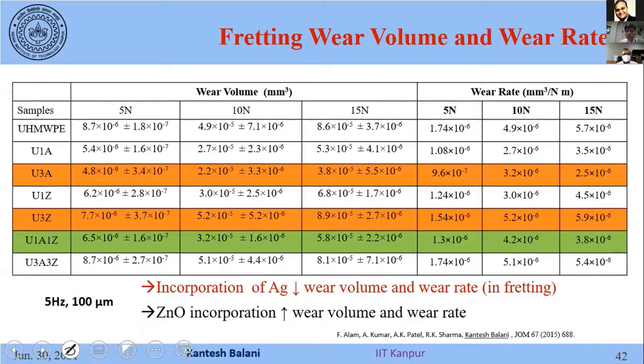Tribology is again very important, at different length scales. Fretting is typically done for contact vibration. There we observe that incorporation of silver is lowering the wear volume. Zinc oxide is actually not so good. It is increasing the wear volume. Why do we add zinc oxide? For increasing the bioactivity. Silver is definitely for antibacterial. Zinc oxide is also an antibacterial agent, but it also helps in bioactivity, but it is increasing the wear rate. So in fretting, zinc oxide is not good, but silver is.